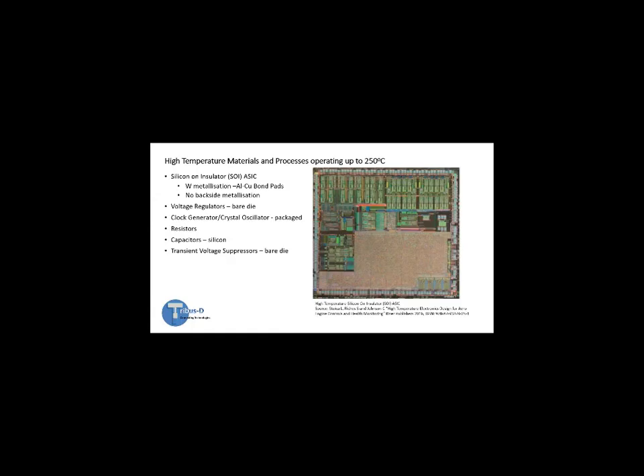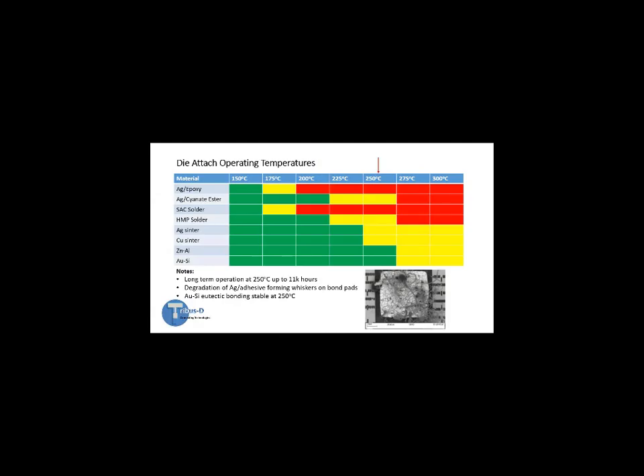In all cases, we were always at the edge of the technology, and we were always finding that things became derated and didn't perform at the high temperatures we expected. But one of the major challenges for getting this long-term operation at 250 degrees C was the packaging side. This is an example of the things we looked at in the development, looking at the whole range of different materials to see what could work at 250 degrees C.